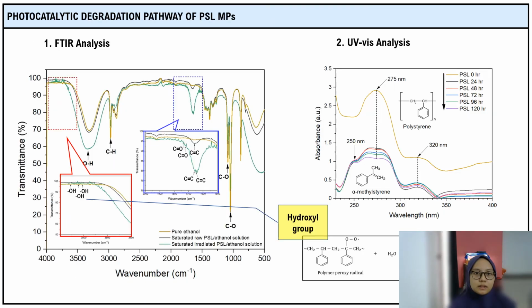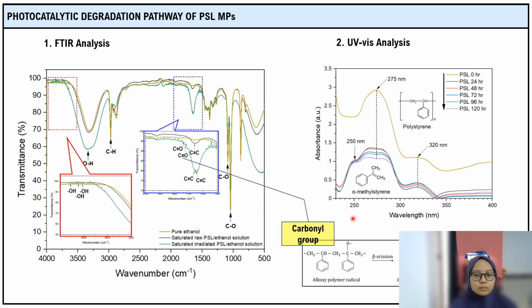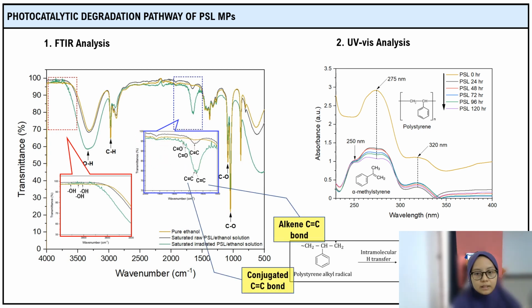The photocatalytic degradation pathway of the polystyrene microplastics was investigated through FTIR spectra, UV-vis absorption spectra, and a radical scavenging experiment. From the FTIR analysis, it was observed that after 8-hour degradation of the polystyrene microplastics, a new hydroxyl group was observed in the form of polymer hydroperoxide. Meanwhile, a carbonyl group was observed in the form of a carbonyl compound, and alkene C=C bond and conjugated C=C bond were observed in the compound alpha methylstyrene.